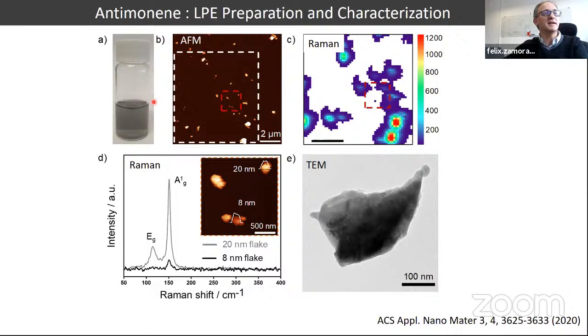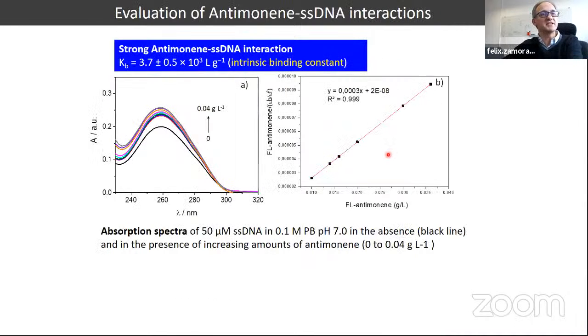trying to produce the material using just one single solvent, because we realized that the presence of water was hampering our experiments. So we were able to produce by liquid phase exfoliation in isopropanol this nice suspension. This is just a material characterization by AFM, Raman, the whole set of techniques. And here I show you the first relevant experiment that we did between our antimonene and a single strand DNA. We first tried to evaluate the interaction between these two systems. And what we found is that as we play with the quantity of antimony, in order to get this plot, we are able to evaluate the intrinsic binding constant of this interaction.